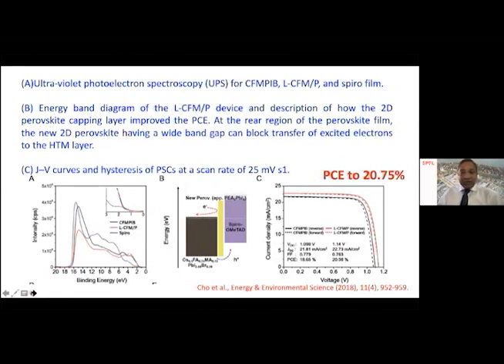Now, if you look at the UPS data, this is on the bottom left. Based on this UPS data, we constructed energy level schemes of these perovskite solar cells. The HOMO level of the perovskite and then the HOMO level of the two-dimensional perovskite, this is the yellow line, is well aligned compared to the hole transporting material, which is significantly lower. And then the LUMO level of the perovskite and the LUMO of the two-dimensional perovskite, followed by the LUMO level of the hole transporting material, is shown here.